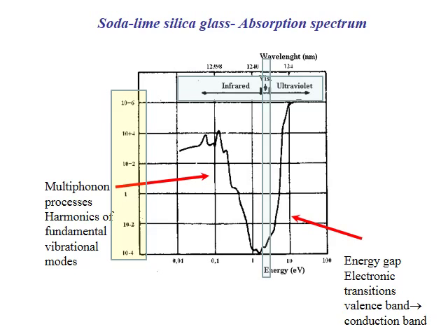You remember that for periodic structures, crystals, phonons with energy of vibrational motions propagate in the material. In glasses, lacking long-distance order, we used to say that phonons cannot propagate. They are localized. I prefer the chemistry language in this case. Localized phonons characterize, in fact, molecular groups. The vibrational modes are molecular ones. The multiphonon process refers then to the harmonics of the fundamental vibrational modes. Therefore, the exact position of the minimum in absorption will be dictated by the chemical nature of the glass.